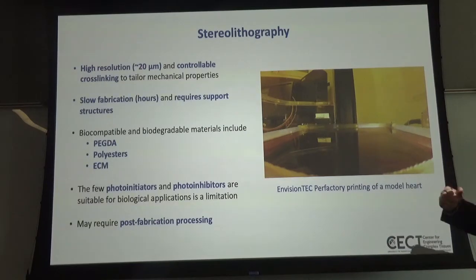It should be noted though, if you're working with a polymer system, maybe you have a cross-linking monomer, you need to add some photoinitiator to take that light energy and probably initiate radical polymerization. That all makes sense. You probably also need to add at least one, if not two, photoinhibitors, so you prevent diffusive cross-linking. So essentially you're cross-linking this pixel here, but not the adjacent pixel,